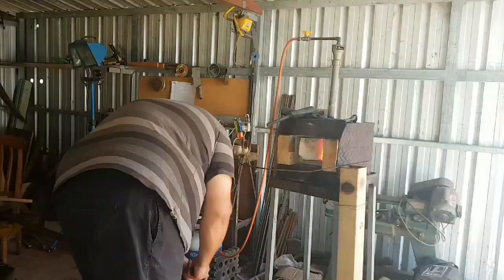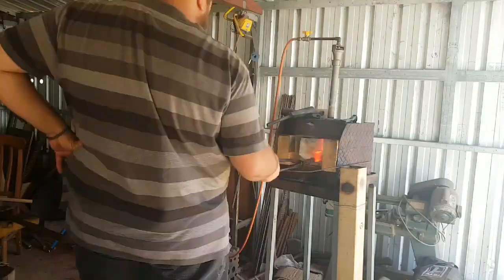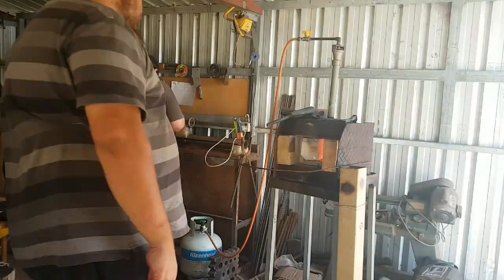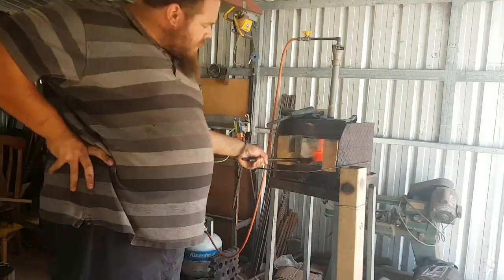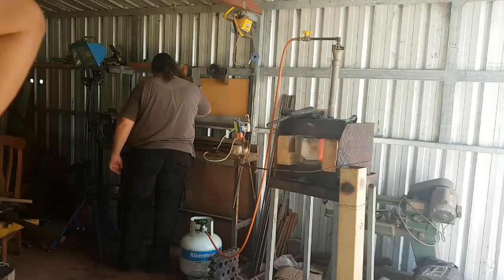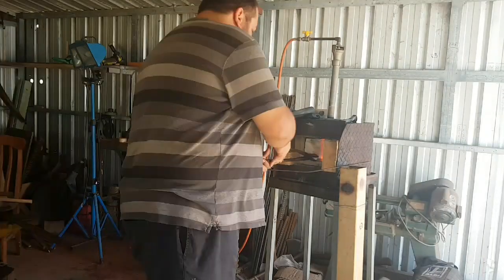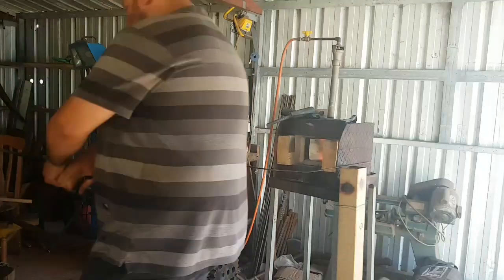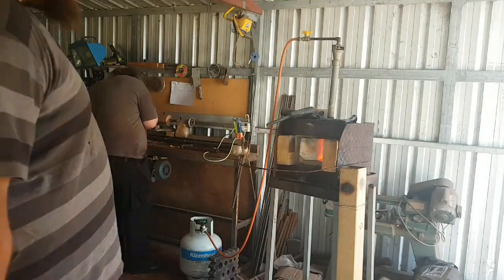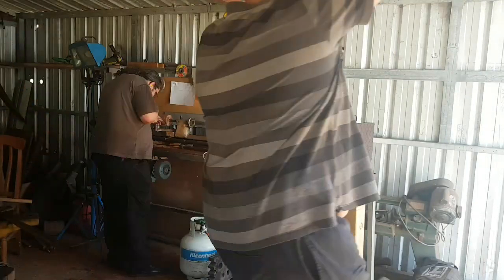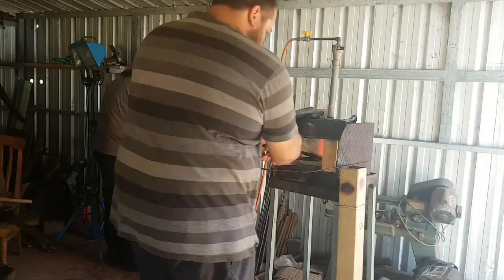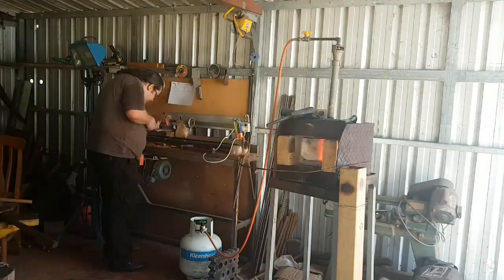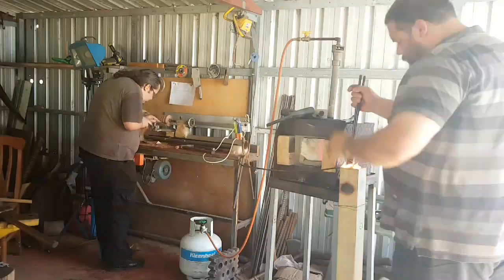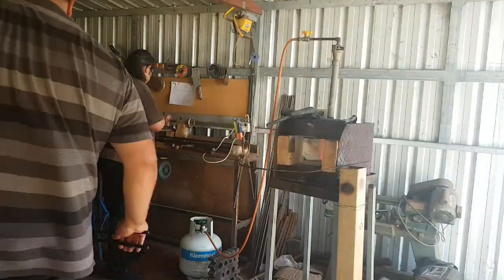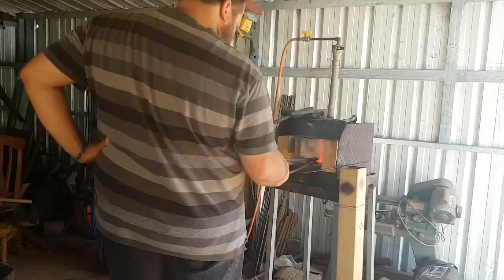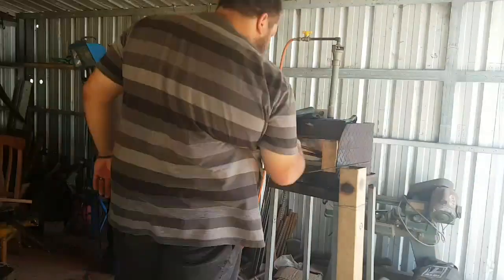But anyway, most of the Damascus blades, being Twist Damascus, twisted in the quench because Twist Damascus tends to want to untwist when hardened as the steel expands and contracts. So I had to do quite a bit of straightening and tweaking just before and after the quench, and I'll have to do a little bit more after temper as well. The blades that I made, being that I left them quite thick and they were only of mono steel, actually stayed relatively straight, which is why I leave them that thick at the beginning.